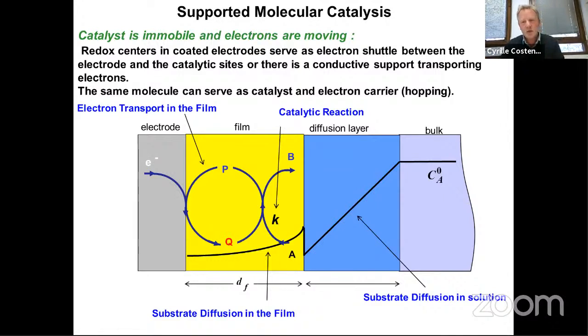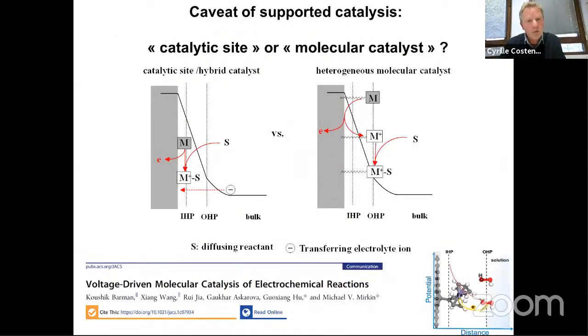And of course, the electron can move because you can have hopping between catalysts, but you can also, of course, put an electronic conductor in the film, and this is usually what people do, okay? So if you put a conductor into the film, now here is the situation. You have a conductor and you have attached your catalyst onto the surface of the conductor. And what is important is to realize that you have two different situations, as I mentioned previously.